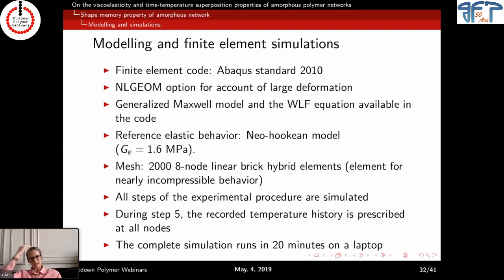Okay, so the modeling was done on the finite element code Abaqus using the Nlgeom option for large deformation. The generalized Maxwell model and the WLF equations are available in the code for finite strain. The reference elastic behavior, so the hyperelastic behavior at a high temperature, was chosen as neo-Hookean with an elastic modulus of 1.6, which we measured experimentally. And what's important is that we are simulating the 5 steps of the experimental procedure: heating, deformation, cooling down, stress release. And for the last step, we recorded experimentally the temperature history, and we prescribed this history on all the nodes.